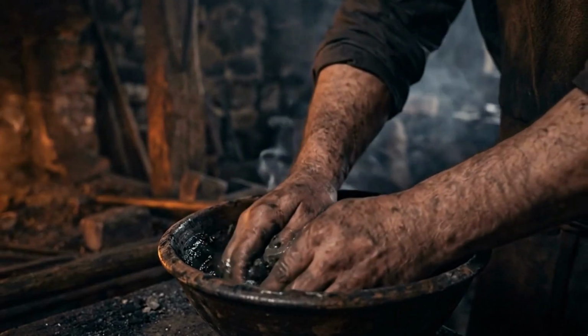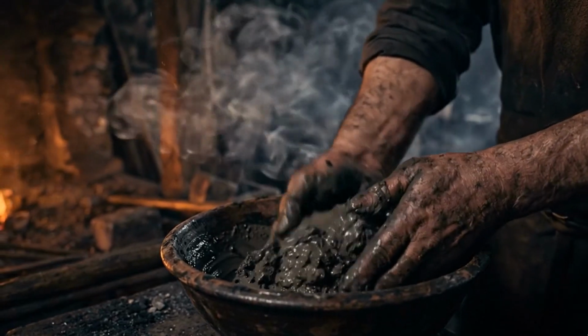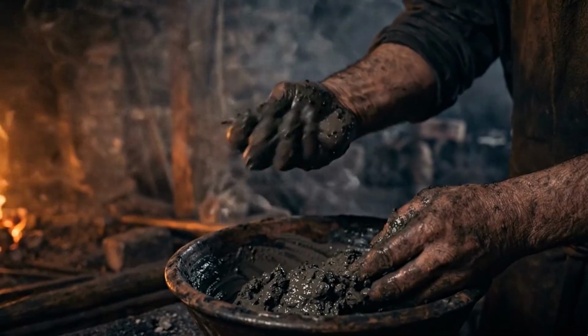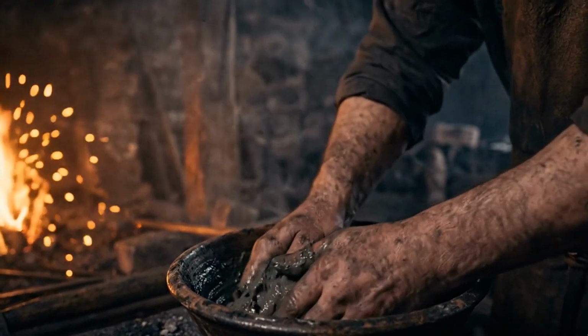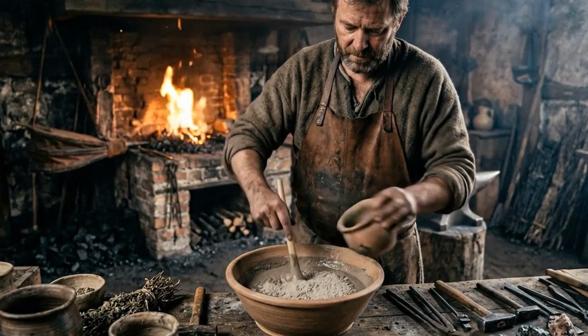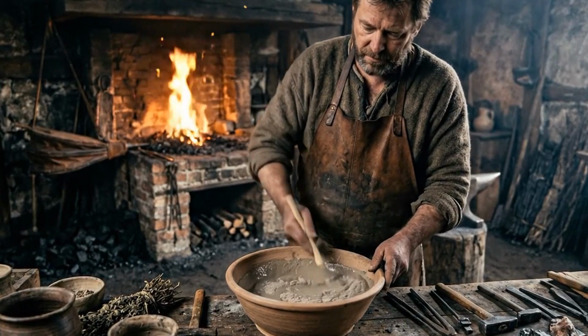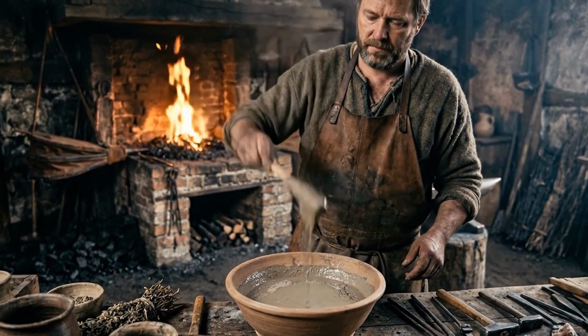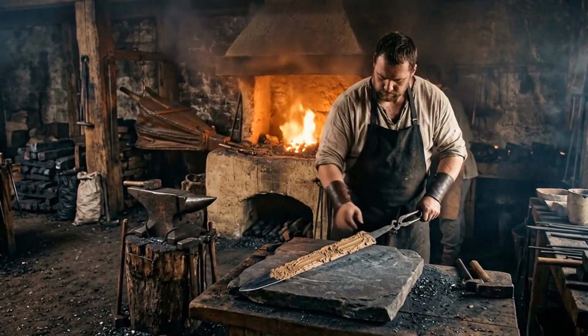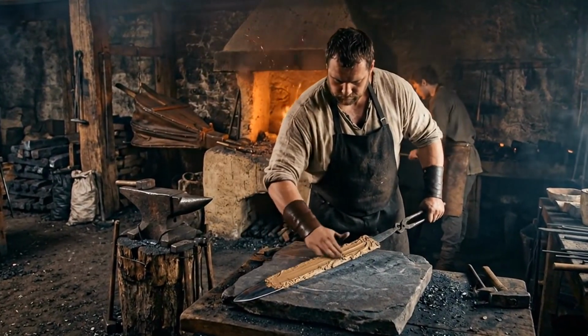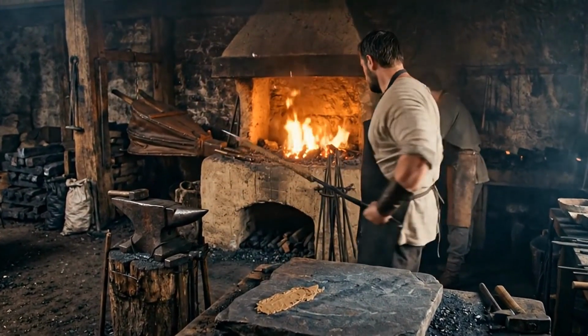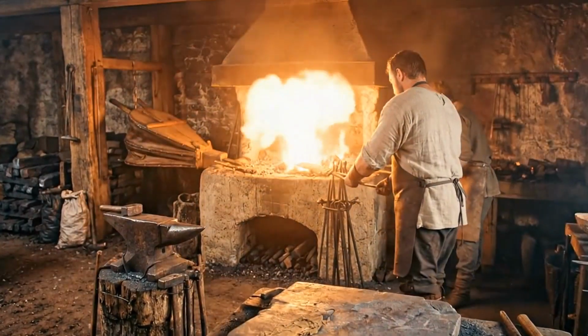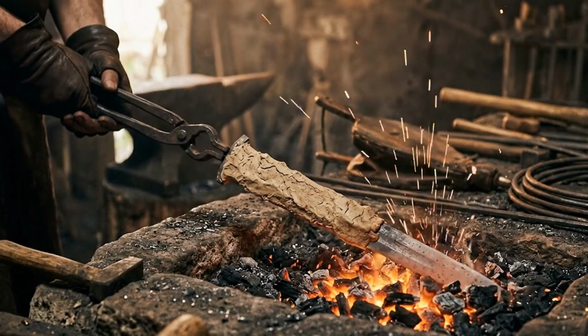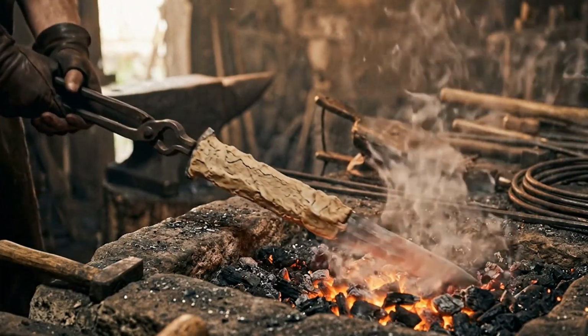The composition of this clay mixture was one of the most closely guarded secrets in any smith's practice, a blend of clay, charcoal powder, and ground stone in proportions that each tradition developed over generations. The differential thickness of the clay coating would determine the rate at which different parts of the blade cooled during quenching, and that cooling rate would determine the final hardness of each zone.